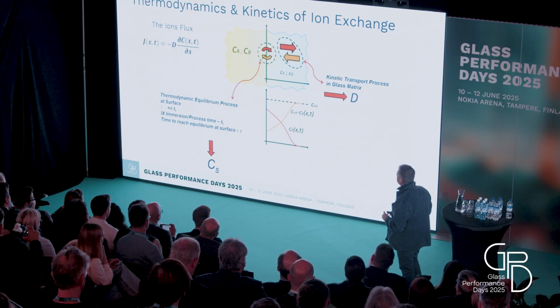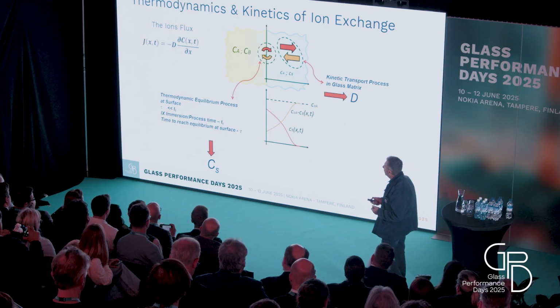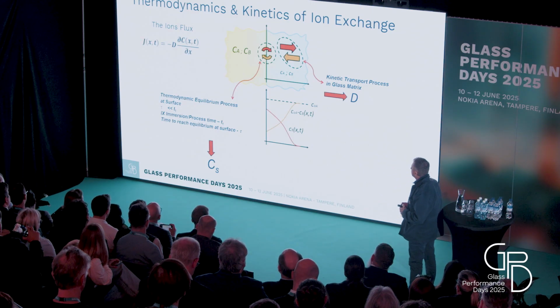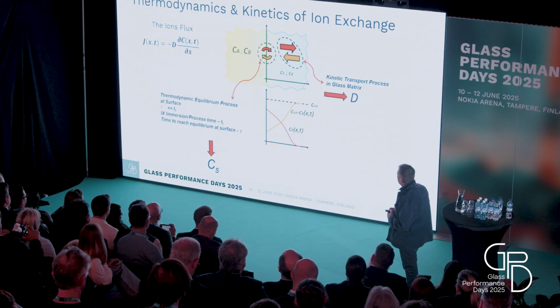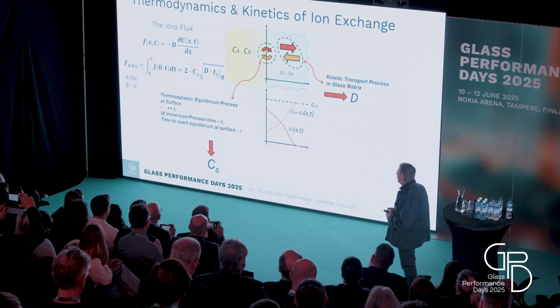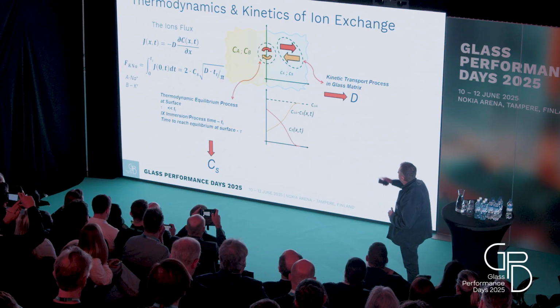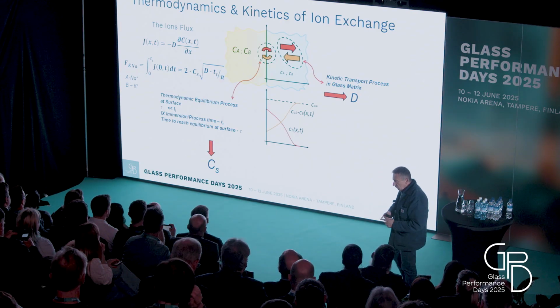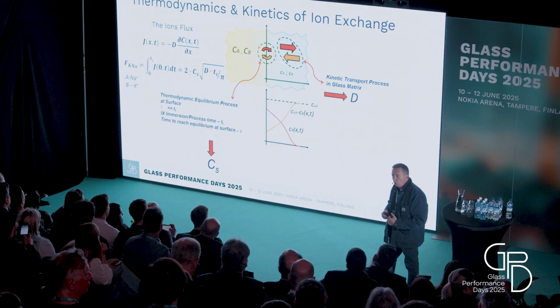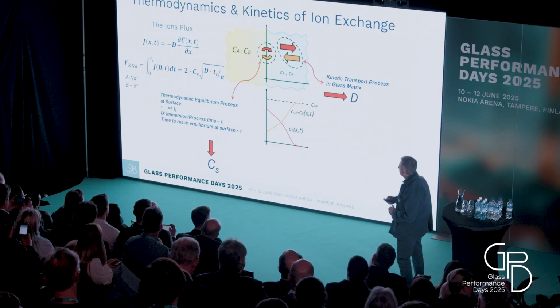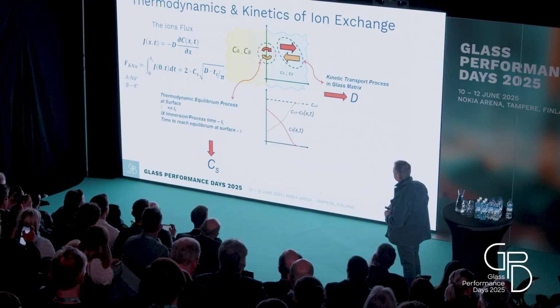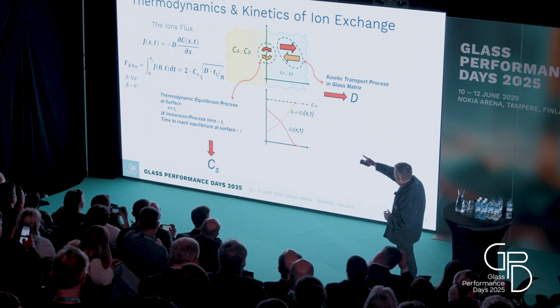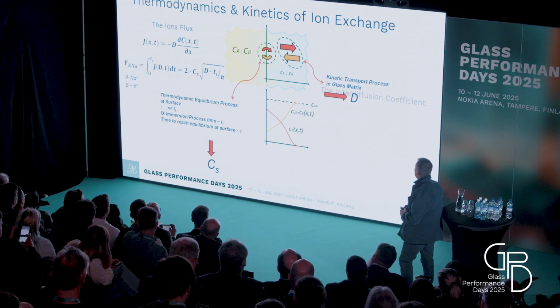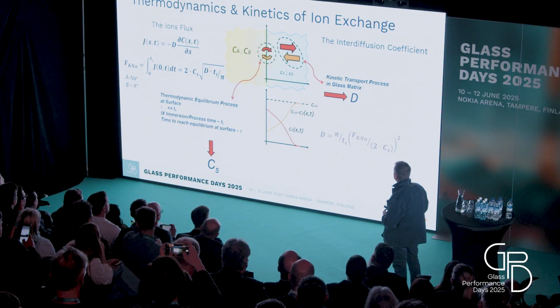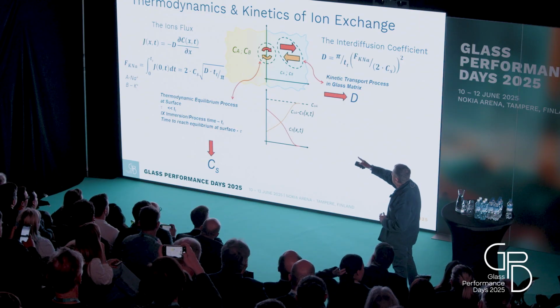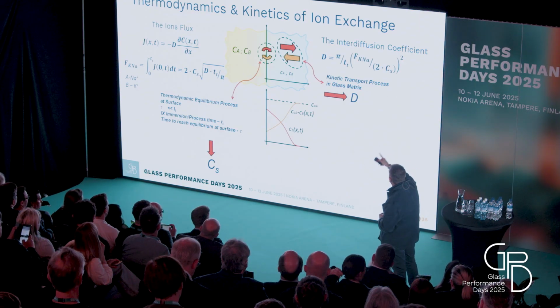So, based on that, we can calculate the ion flux through that equation, that is a Fick equation. Again, it's an approximation. And you can integrate, if you take the flux at the surface and make the integration over the total time of contact, then you have the total flux that has been exchanged. Under that approximation, it is that equation. The interdiffusion coefficient that plays a role can be calculated from that equation, and is this one.